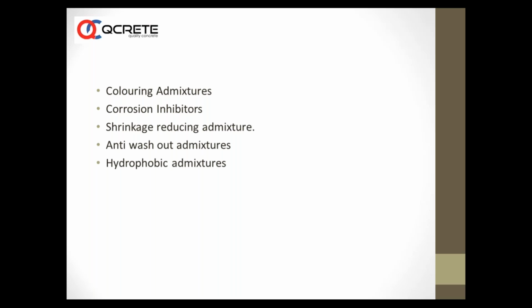Now we have the latest kind of corrosion inhibitors called migrating corrosion inhibitors. There are two varieties of migrating corrosion inhibitors. One can be mixed along with the concrete to improve the corrosion resistance, where this chemical migrates literally and collects itself on the reinforcement bar, gives a passivating layer around the steel rod and reduces the corrosion, delays the corrosion, prolongs the life of the structure. So most of the piles done in countries like the Middle East and other countries where there are a lot of problems of corrosion, or even now in India, many of the structures where there is a requirement of high corrosion resistance, marine structures and all, have started specifying corrosion inhibitors.